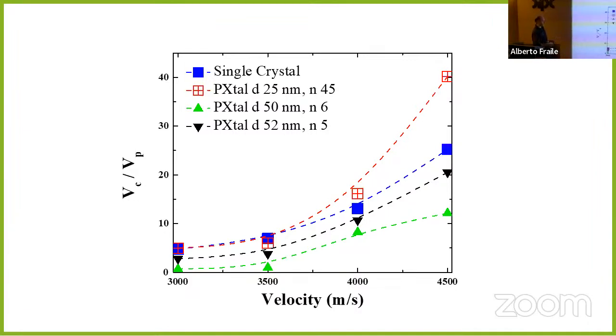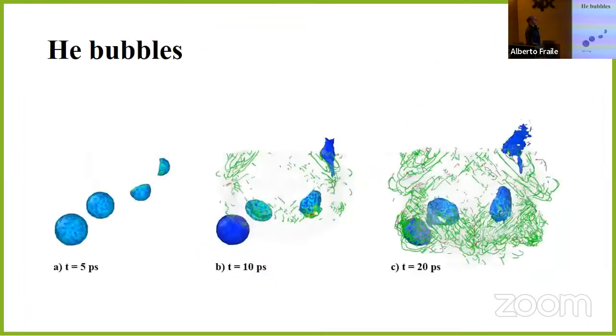You can do another sample with 5 nanocrystals, but these nanocrystals can be different orientations and everything, so the result can be maybe very different. So just to finish, we can do more, and we can also add helium bubbles, for example, in the target, because in the material you will have helium and tritium, and you can have different things in the real tokamak along the time. So if you have helium bubbles, this is the shockwave that is being generated here after the impact, and then you have all the dislocations generated here. So the interaction of the dislocations with the helium bubbles and everything is quite complex.